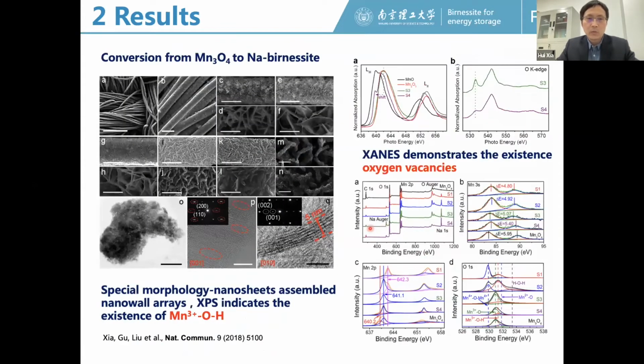After that, we try to figure out why. What is the difference? So first, we're looking at the morphology of this sodium Birnessite. We can see this material has the normal morphology for Birnessite. The material is composed of ultrathin nanosheets, and from this oxygen X-ray absorption near edge spectra, we can see that for the S4 sample, this oxygen pre-peak is greatly reduced as compared to the S3 sample, which indicates that we successfully induced oxygen vacancies in this material by heating it in the argon atmosphere. So this can actually improve the electron transfer in this material.